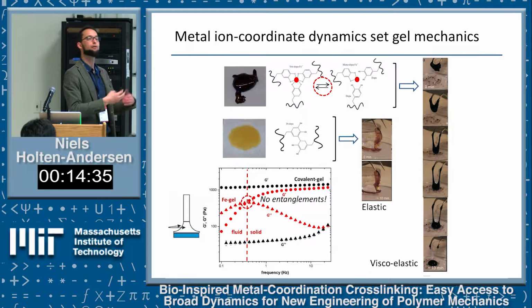You can get viscoelastic properties in something like silly putty because you have really long polymers that wrap around each other. We have really short polymers, but the reason they still behave like silly putty is because of the dynamics of this crosslink. The amount of time you spend in the cross-linked state versus the uncross-linked state dictates these viscoelastic properties. That's how we control this fluid-solid transition.